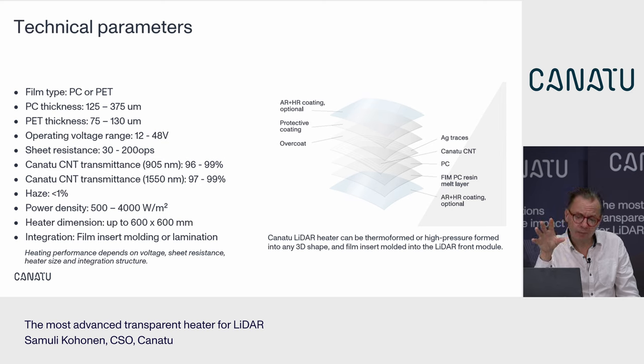Haze level of 1%, and power densities vary typically from 700 watts per square meter up to 3.5 kilowatts per square meter. We can build up to 600 by 600 millimeter heaters, but as you all know, a typical ADAS heater is roughly 150 millimeters by 30 millimeters. But of course, if there is a need for bigger heaters, that can be done. And integration is really by film insert molding or lamination.